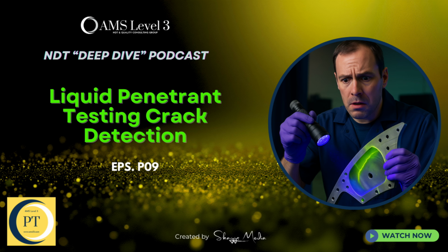And the third method, you said often higher sensitivity, but more control needed. Right. Those are the post-emulsifiable methods. Here, the penetrant itself isn't washable. You apply it, let it dwell, remove the gross excess maybe, and then you apply a separate emulsifier agent. Okay. An extra step. An extra step, but it gives you more control. Method D, which uses a hydrophilic or water-based emulsifier, is generally considered the most sensitive. It usually involves a quick pre-rinse with water first to get most of the surface penetrant off before applying the emulsifier. Like pre-washing a greasy pan. Kind of, yeah. It makes the emulsifier's job easier and more controlled.